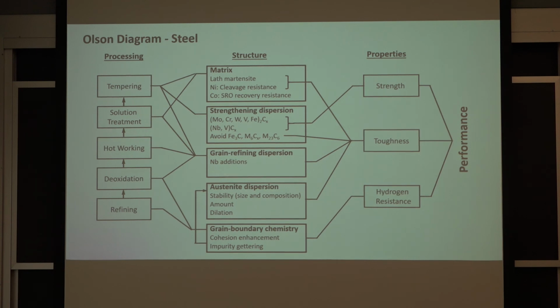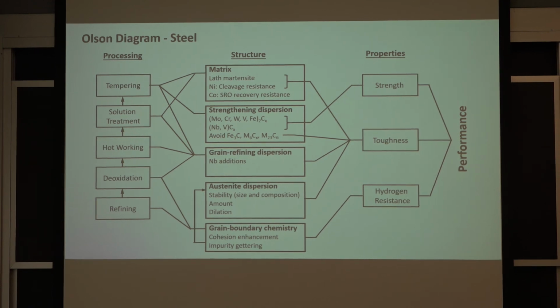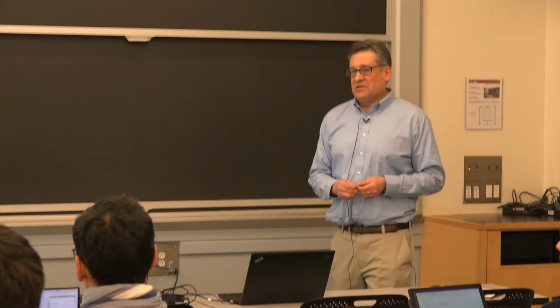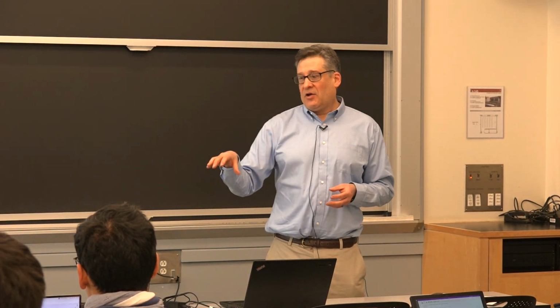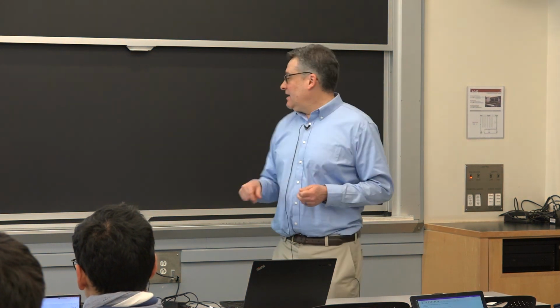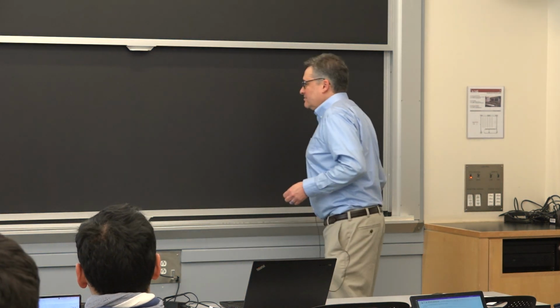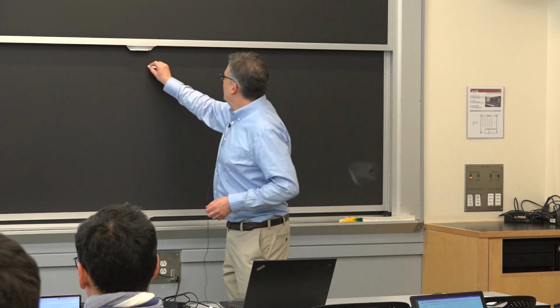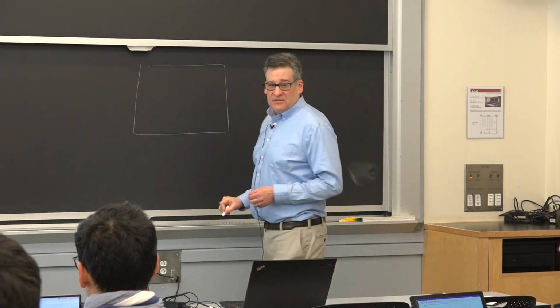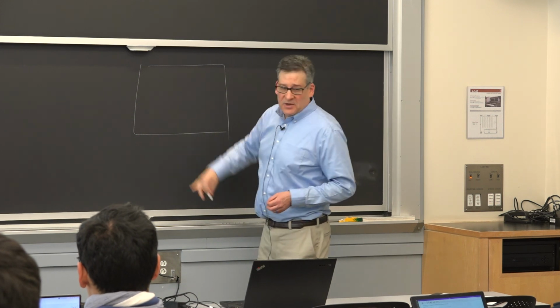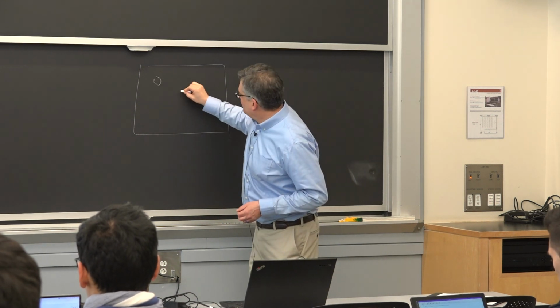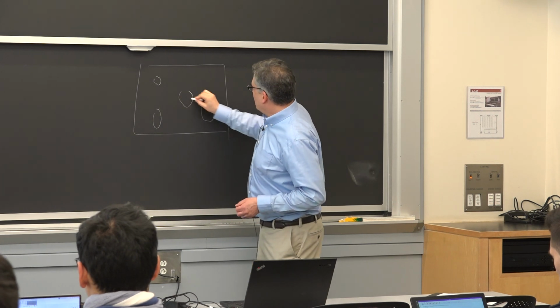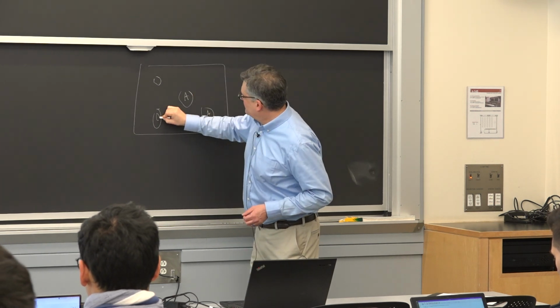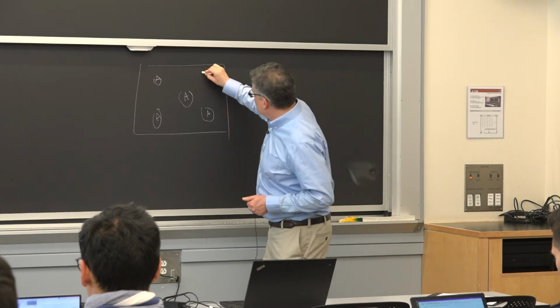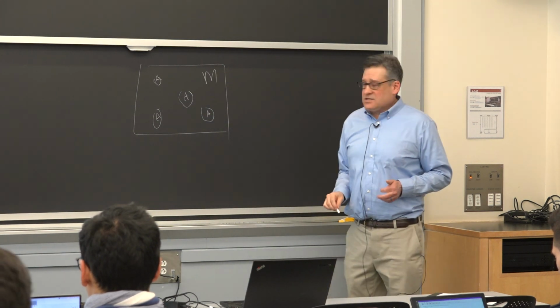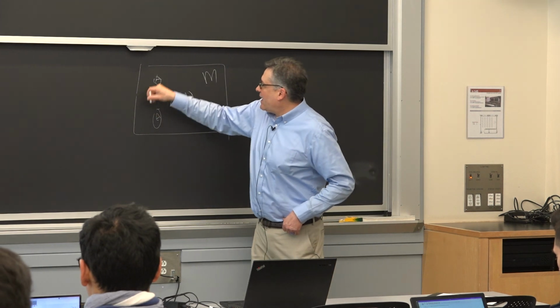Some of it stays austenite. That's important because during the transformation from austenite to martensite, there's actually a volume change. If you have a microstructure, and suppose all this is martensite, and you've got a couple of grains of austenite in here, and then this is martensite, and this material gets a crack...